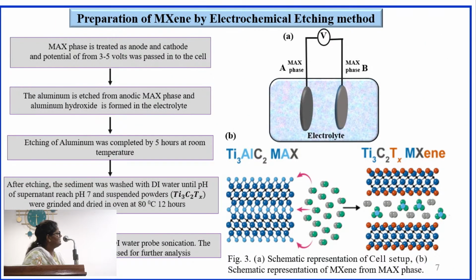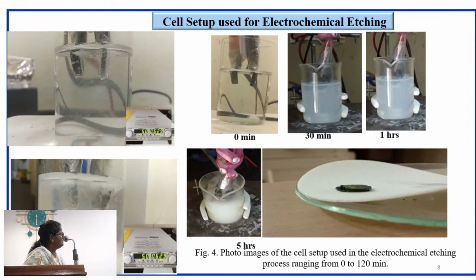Then the sintered MAX phase was subjected to electrochemical etching using acidic and alkaline electrolytes, through an anodic oxidation reaction carried out from 3 to 5 volts. The anodic MAX phase is etched in the electrolyte while applying a potential, and MXenes form with terminal groups based on the etchant.